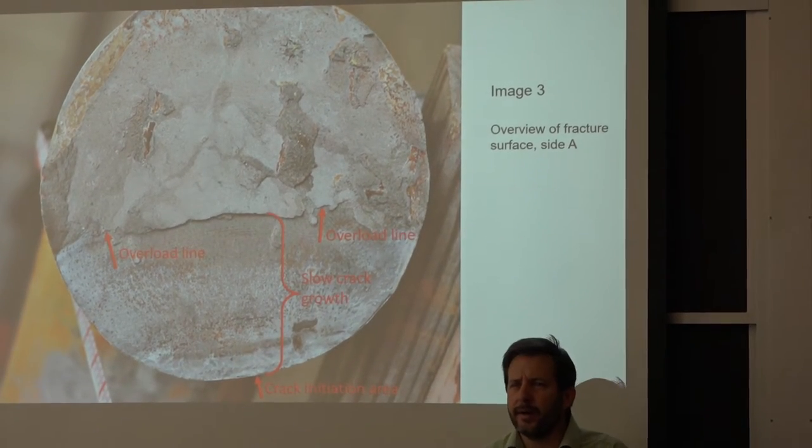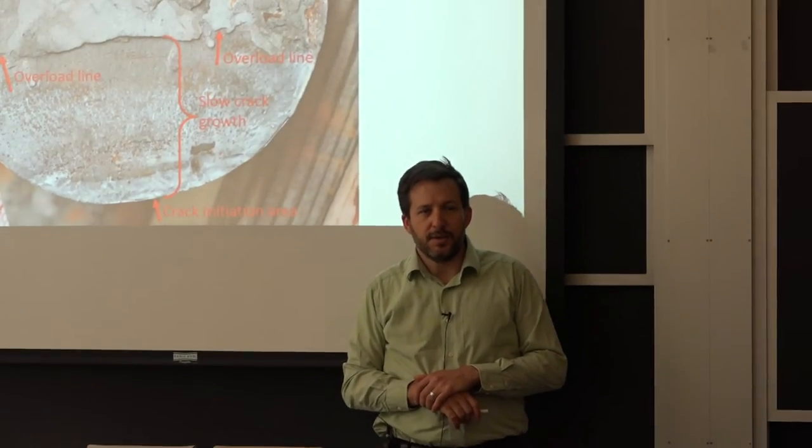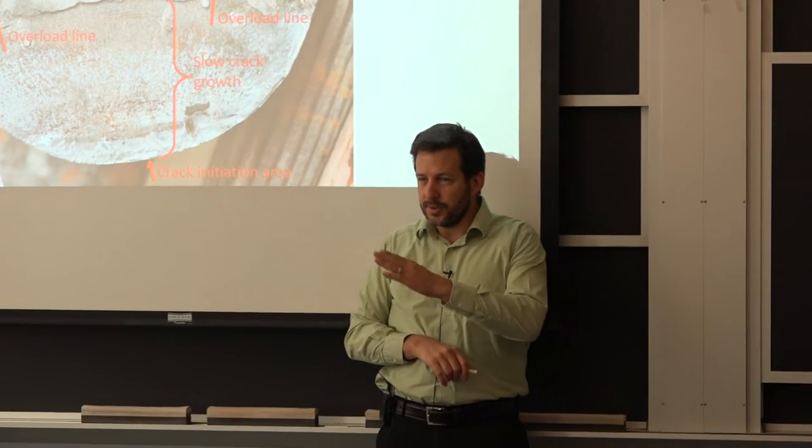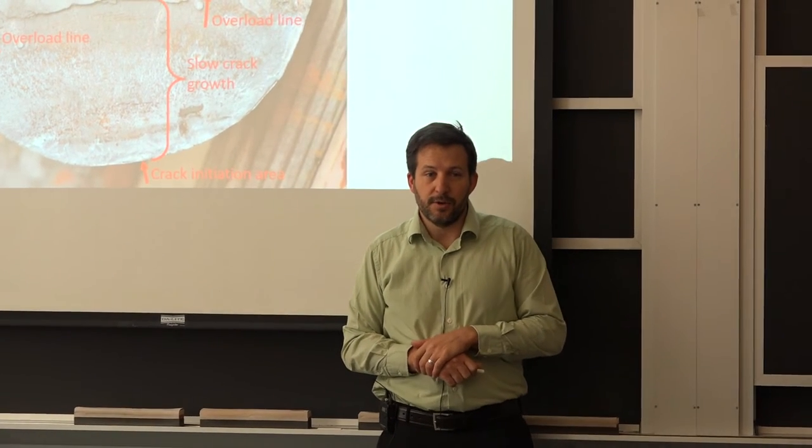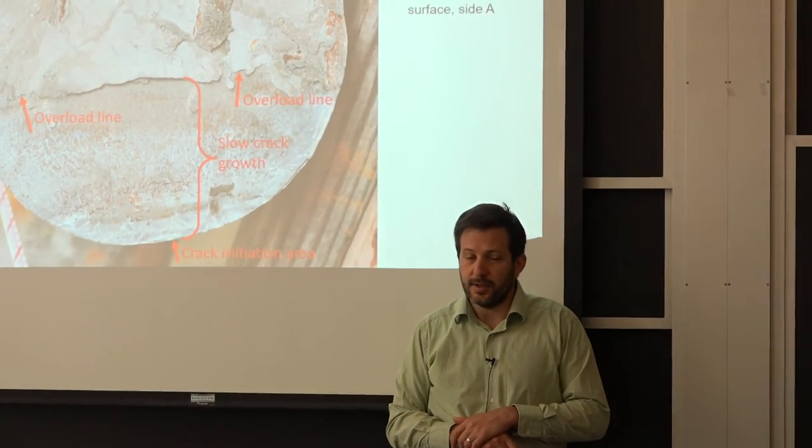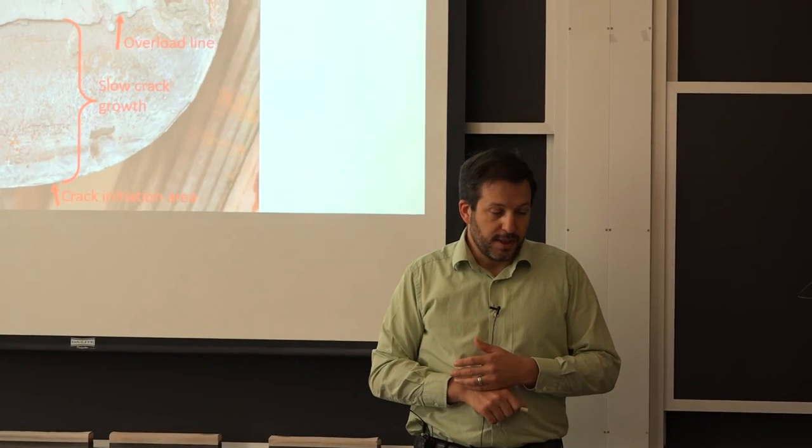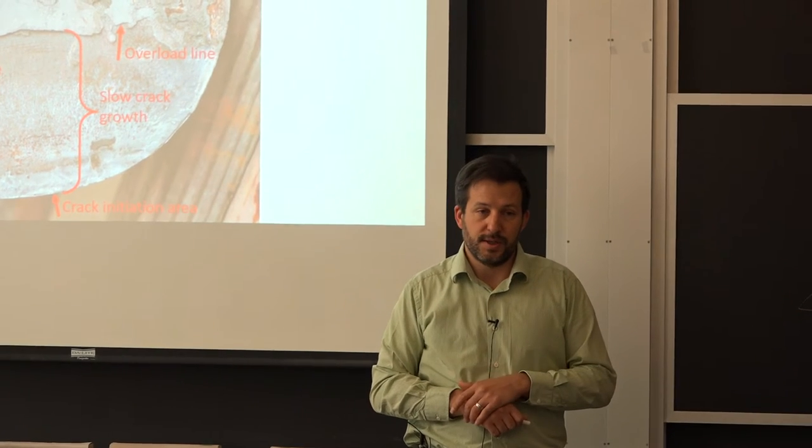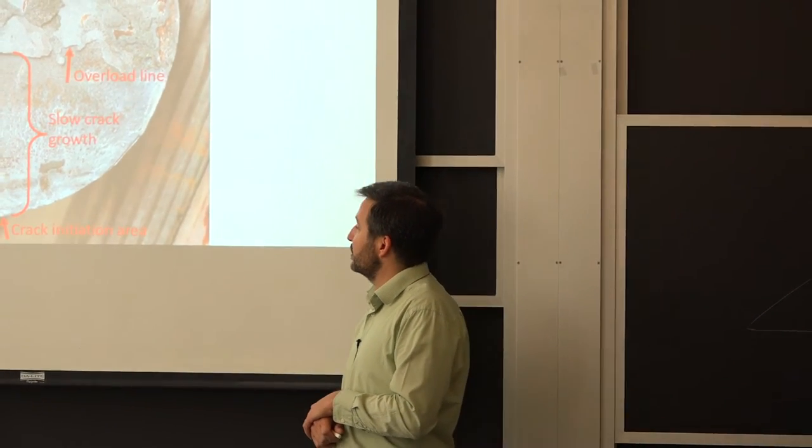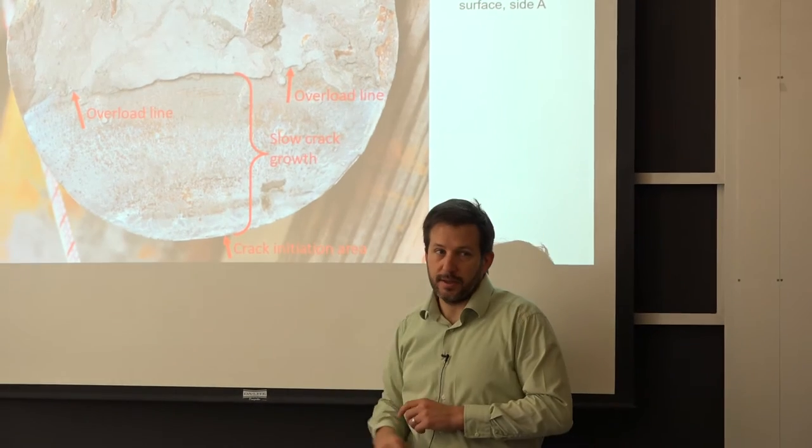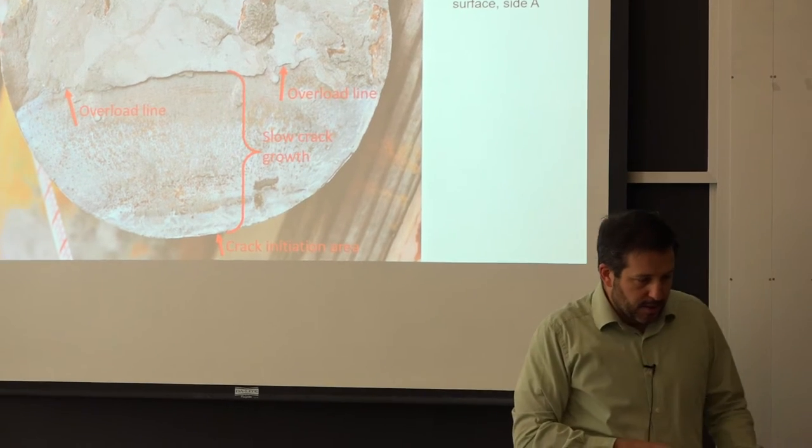So what do we have to learn there? It's not really a pure overload in the sense that you were able to have a crack 40% through and the chain was still holding the load. If somebody comes and says there wasn't enough metal or the metal didn't have a yield strength that was high enough, well it doesn't quite work because you were able to take on probably twice as much load if there wasn't any crack in this chain.